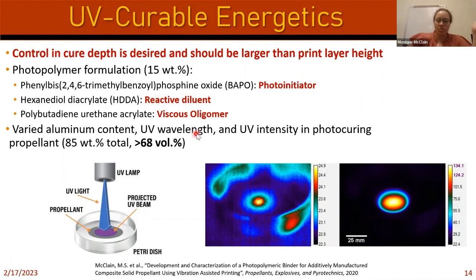And in general, our mixture has to be able to handle opaque additives, because in propellants, even though the majority of the particles are ammonium perchlorate, which are clear crystals essentially, you will have opaque additives like iron oxide or aluminum. The content of that could be around 15%, for example. So that does need to be accounted for here. It has to cure reasonably deep if there are some opaque additives.